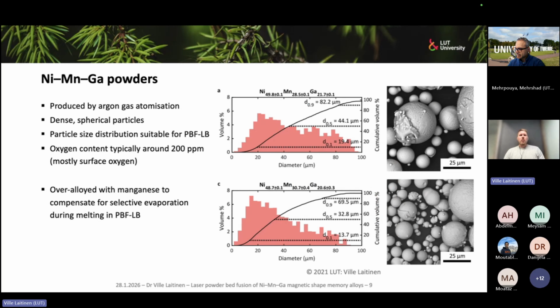The type of feedstock we typically use for laser powder bed fusion is argon gas atomized spherical nickel, manganese, gallium powders. The advantage of this gas atomization process is that we get very dense, circular-shaped spherical particles. These are very good for the laser powder bed fusion process itself from the spreadability point of view, and also we are not bringing any inherited porosity with the particles themselves.